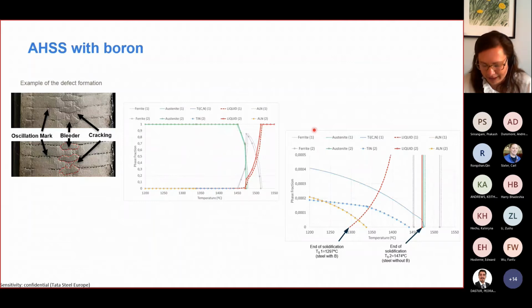Another short and quite interesting example is an advanced high-strength steel with boron. Boron is at levels, again, in ppm. Could be 20, 30, even 50 ppm boron. But it's ppm level, so it's a very, very low amount. However, boron is an element that highly influences the solidification of the steel. If you have boron in combination with manganese, it could broaden widely and extend enormously your solidus temperature, up to the point, like in this case, where Thermo-Calc says we have it close to 1300 degrees. So we have a huge solidification range.